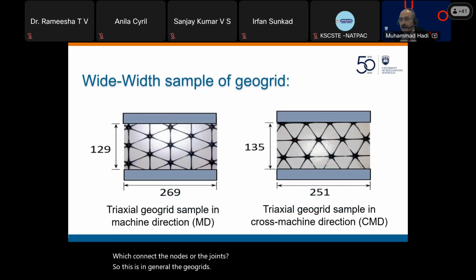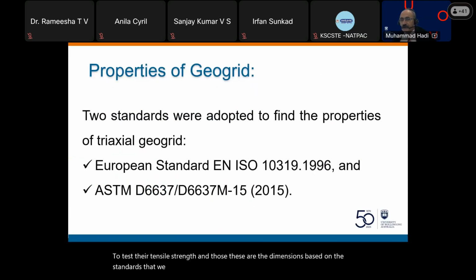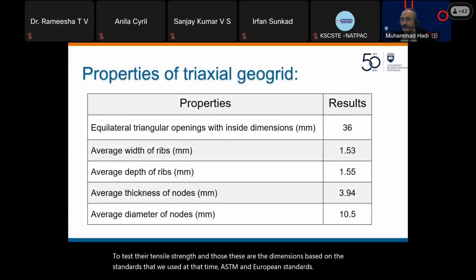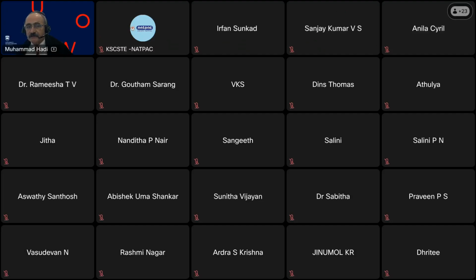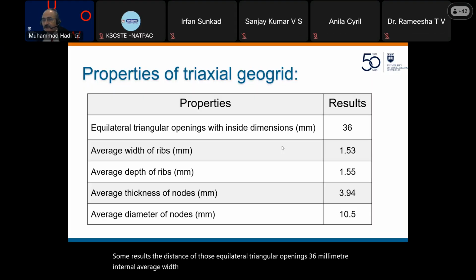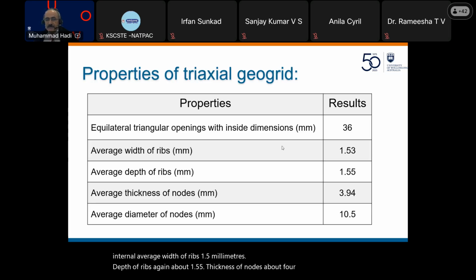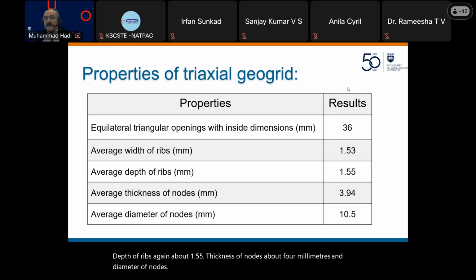So we had samples to test their tensile strength. And these are the dimensions based on the standards that we used at that time, ASTM and European standards. Some results: the distance of those equilateral triangular openings, 36 millimeter internal; average width of ribs, 1.5 millimeters; depth of ribs, again, about 1.55; thickness of nodes, about 4 millimeters; and diameter of nodes, about 10 millimeter.